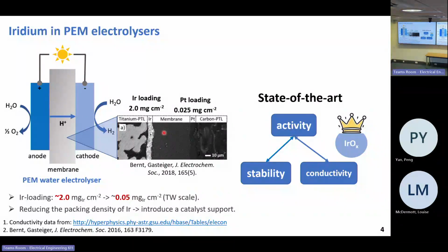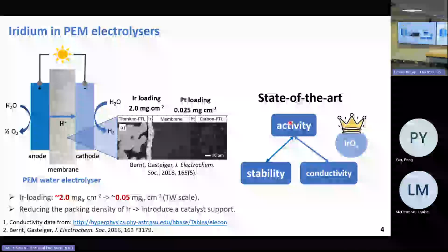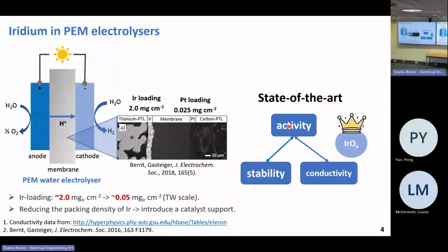As mentioned before, it's challenging to find a stable and conductive support for iridium because most materials will go through oxidation, subsequent passivation, and dissolution under OER conditions. Iridium has achieved a good balance between activity, stability, and conductivity. That's why it remains the state-of-the-art OER catalyst and seems to be irreplaceable.